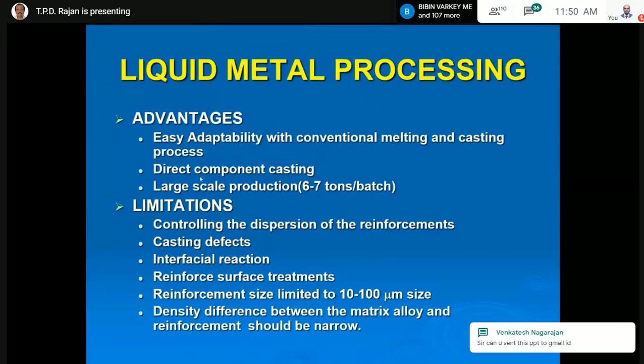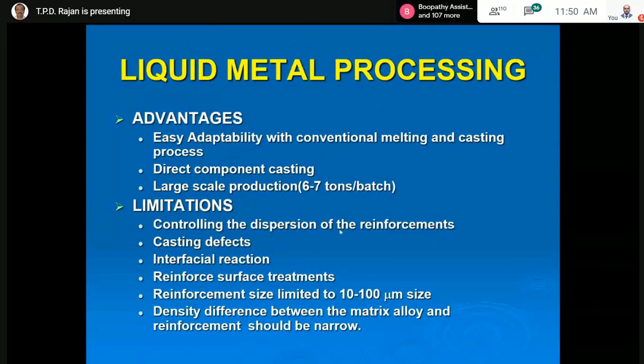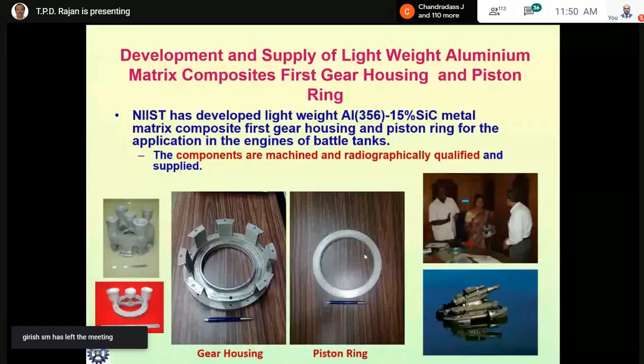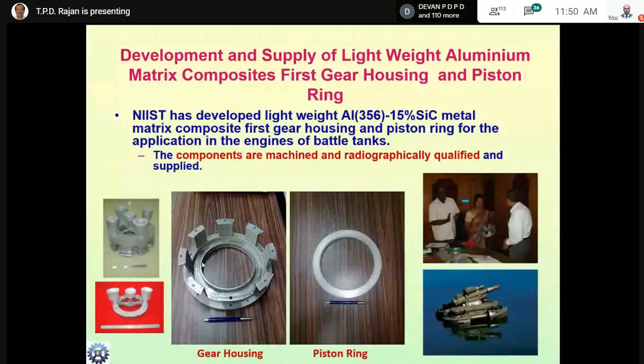It has easy adaptability and direct component casting is possible. However, the limitations are controlling the dispersion of the reinforcement, casting defects, interfacial reactions, and the need for reinforcement surface treatments. So this is a typical aluminum SiC composite gear housing made by liquid metal casting and sand casting. After sand casting, it looks like this, and when we machine it, it is converted to very nice gear housings and piston rings.